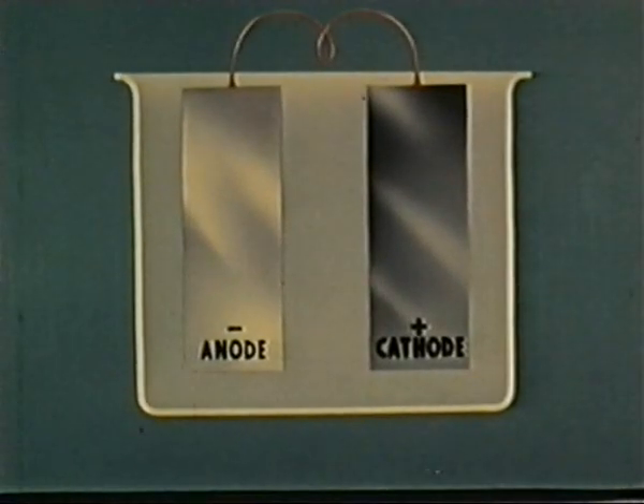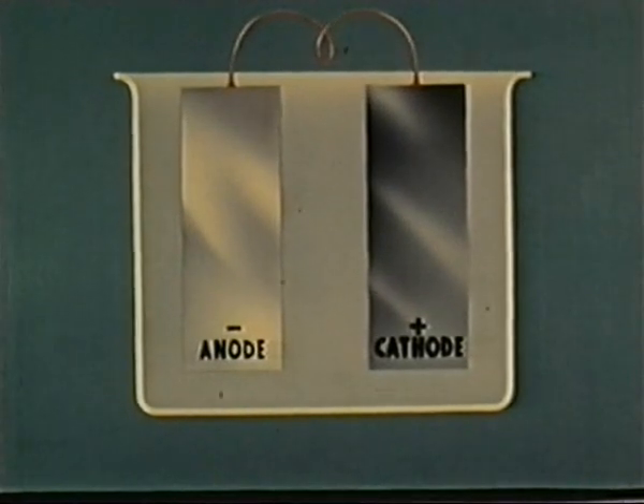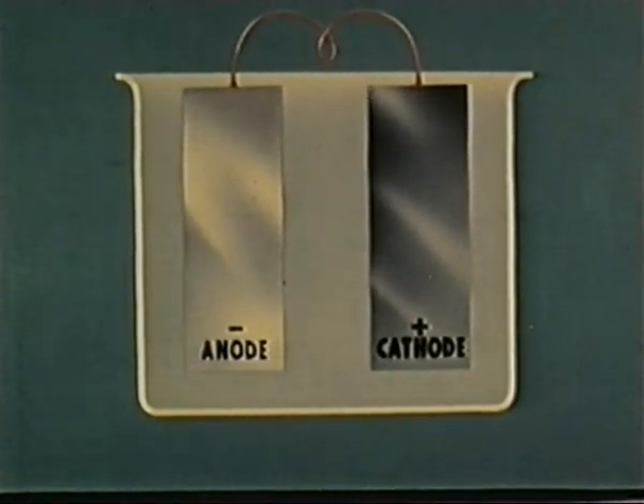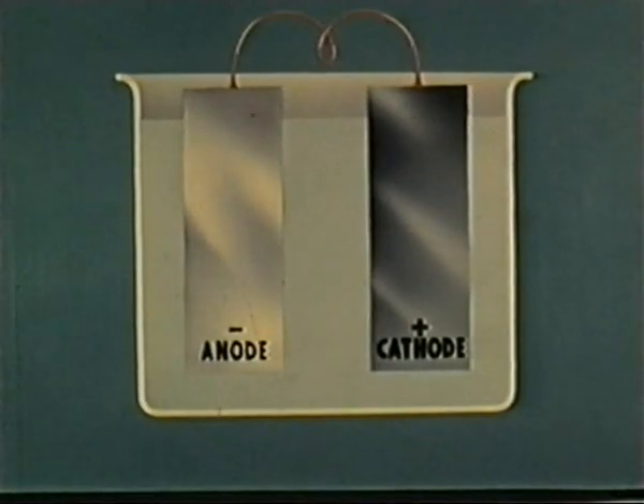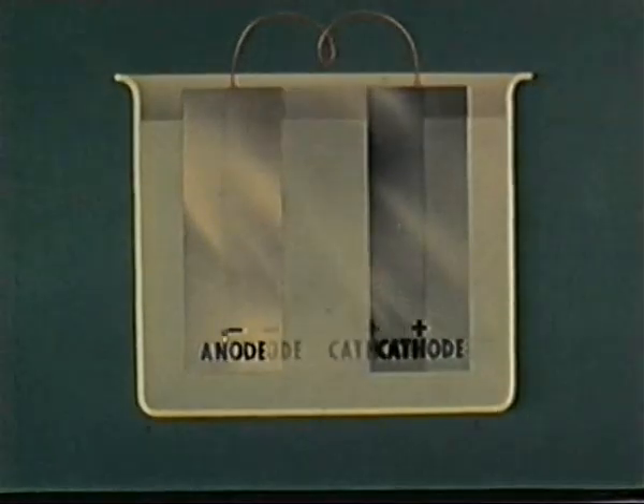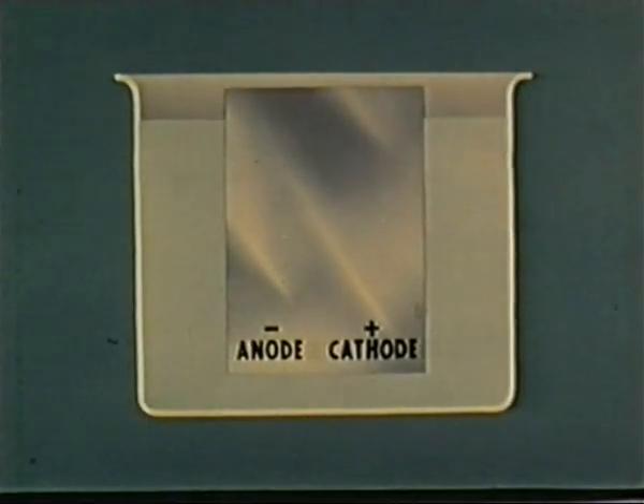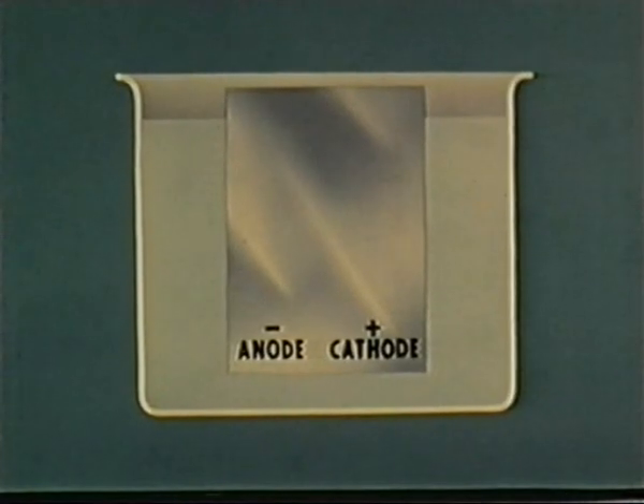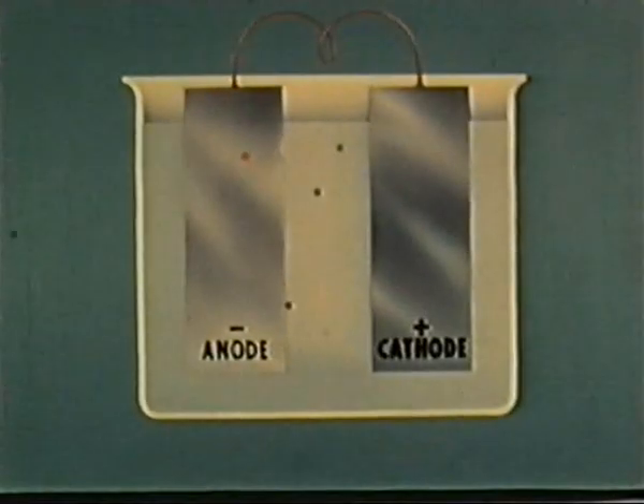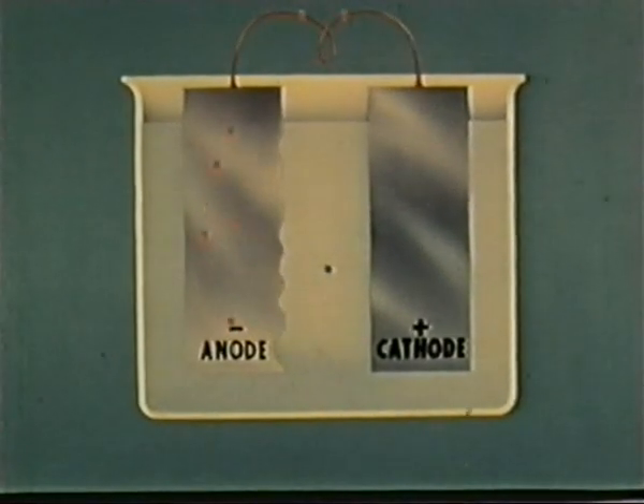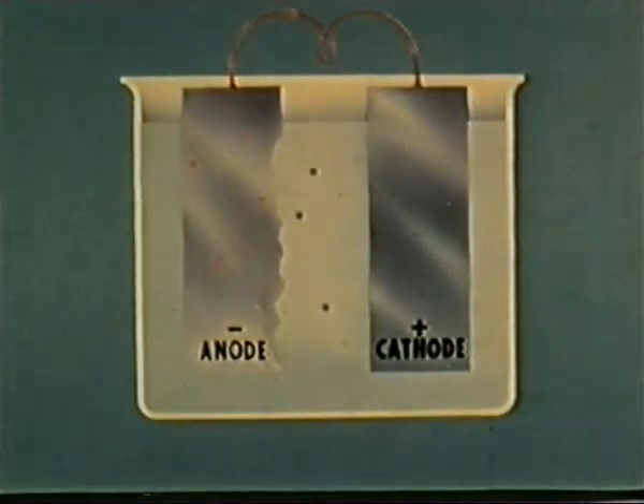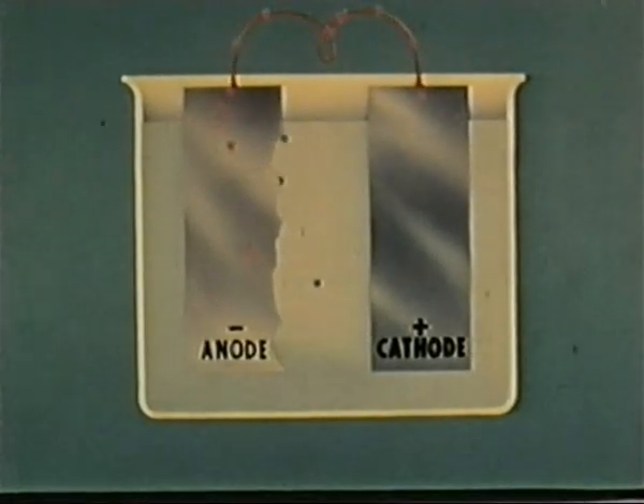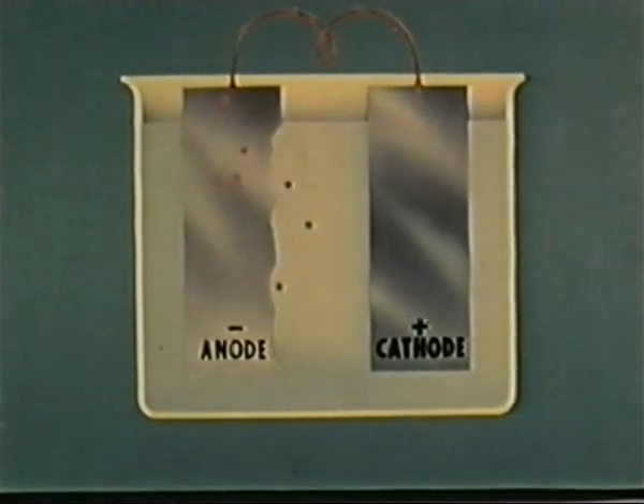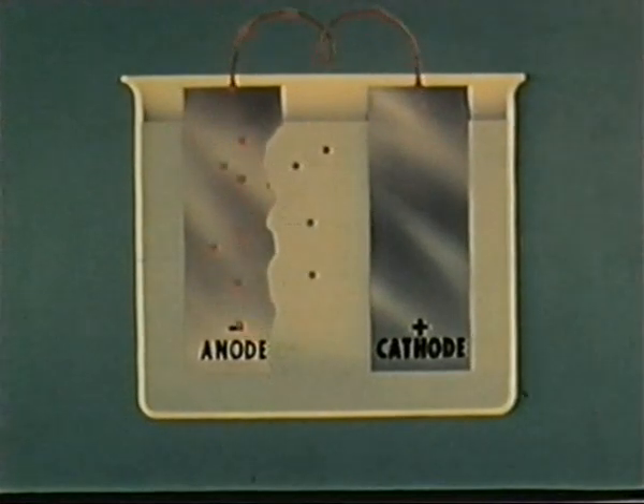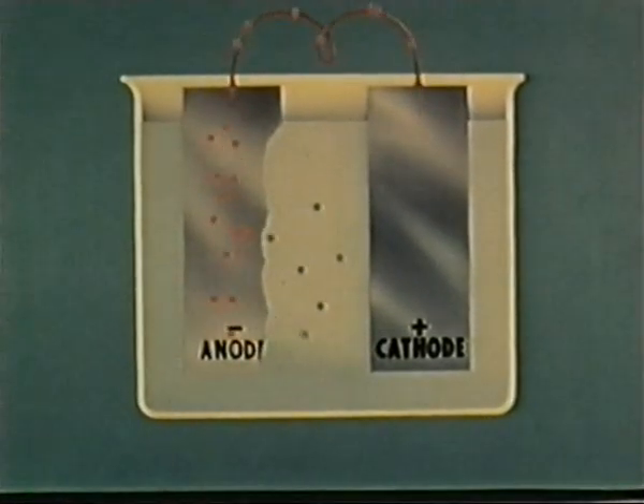The more we study corrosion, the more we realize two important facts. First, that corrosion is a natural process that can occur whenever there exists in an electrolyte a difference in the electrical potential of dissimilar metals, or a potential difference between separate points on a single metal surface. The rate of attack will be determined by the composition of the environment and other factors such as polarization, velocity, and temperature. Second, that corrosion can be controlled and avoided when we understand the conditions that cause corrosion currents to flow.